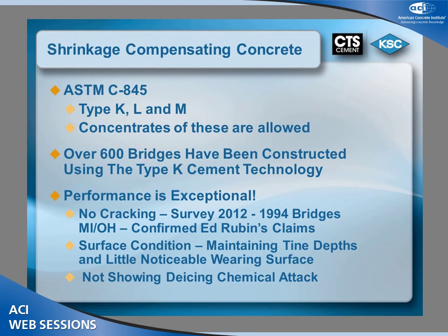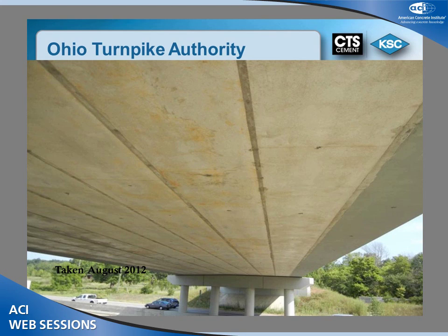So with ASTM C845, we've got 600 bridges and counting. We've actually lost count of the number of bridges that are out there, and the performance is excellent. This confirms Ed Rubin's paper in regards to crack-free concrete. The surface condition, we're actually seeing the tines being maintained throughout these decks, and little noticeable wearing on those surfaces. They're in pristine condition. And we're not showing fault from the de-icing chemical attack, which leads us to want to ask the question, is the porosity of this concrete lower than that of the concrete of type 1 or type 2 Portland cement? And going back now to some of the study that was conducted this year in Ohio,